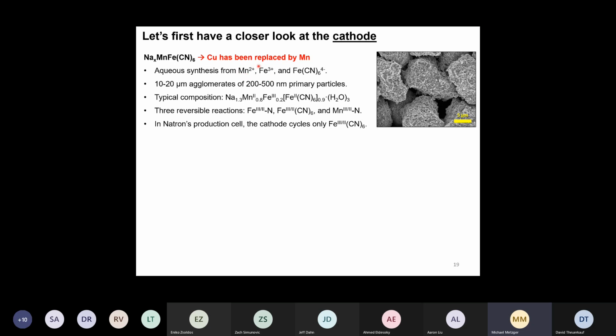You have a manganese 2+ precursor, an iron 3+ precursor, and a hexacyanoferrate precursor. Typically people use co-precipitation. So you just mix these precursors together, and what precipitates out is your active material in the desired crystal structure, if you do everything right. And we already mentioned, these are maybe 10 to 20 micrometer agglomerates, with maybe 200 to 500 nanometer primary particulates that make up these agglomerates.